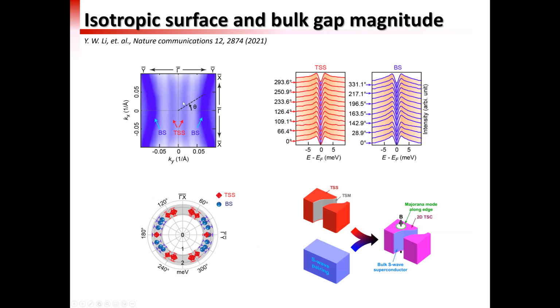In addition to the magnitude of the gap, we also study the anisotropy of the gap. Because with ARPES we can measure different momenta, we can measure the gap magnitude versus the in-plane angle. And then we plot this gap magnitude. On the right-hand side, you can see that the gap magnitude doesn't really vary with direction in momentum space. Also, you can see from the bottom left panel that this looks like a homogeneous gap without a node.